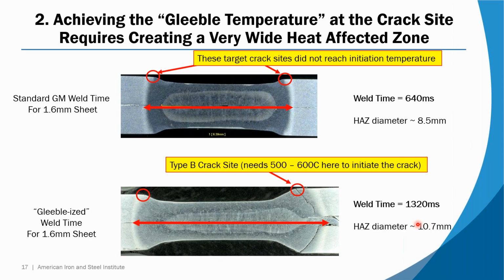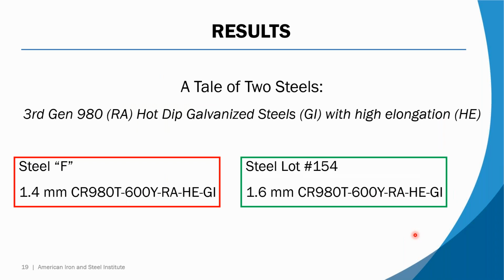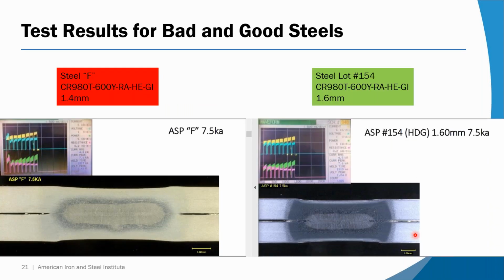This is 10-11 millimeters of heat affected zone. So yes, there is an effect of thickness on these parameters, but we've boxed that into 2 thickness ranges, nominally 1.1 plus or minus 0.1, and 1.5 plus or minus 0.1. We got good correlation with the way the procedure is written for that entire range of thickness. So it didn't really affect the results that I showed you, the fact that one was 1.4, the other was 1.6. You can see the nuggets are roughly within striking distance, whether it's the material on the left or the right.